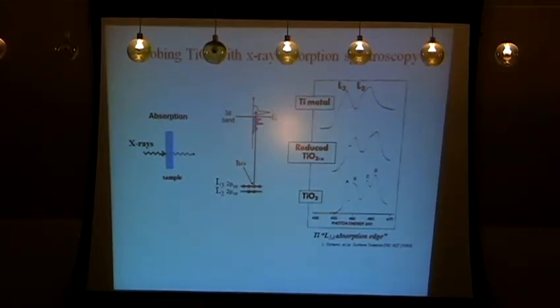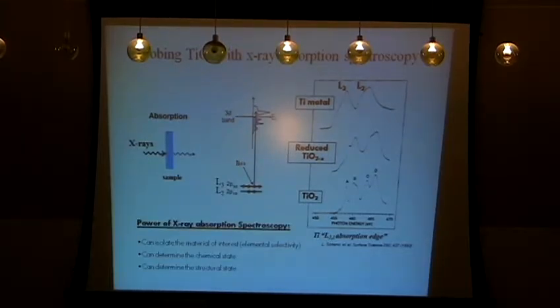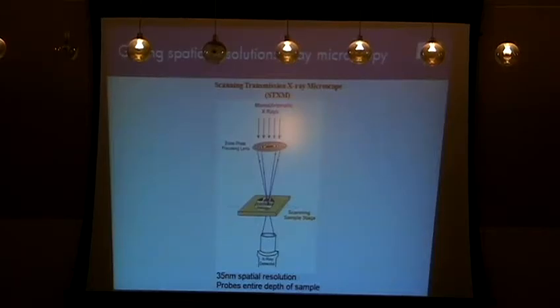And so here's a number of titanium absorption spectra for different chemistries. We start with titanium metal. What you see here is two broad absorption peaks, and these two absorption peaks are called the L3 and the L2, and that actually just corresponds to the two different core levels that you're exciting from. Now if we put oxygen in the mix and we actually have this titanium ion surrounded by oxygen, you actually get a change in the unfilled valence orbitals that are allowed. So for example, in this case, you see that these two broad peaks are actually splitting into four peaks, what's called the crystal field split. And all the way to stoichiometric titanium dioxide, you see very strong crystal field split peaks. And in fact, you can actually get structural information. So this, for example, is actually the anatase phase of titanium dioxide, and that's evident from this peak splitting. So the main message is that with X-ray absorption spectroscopy, you basically can get a fingerprint of what the chemistry and structure is of the device. So with this technique, we're able to, just by tuning the energy to the material that we want to study, we can actually isolate the material that we're interested in, and from that, we can actually get the chemical and structural state of the material.